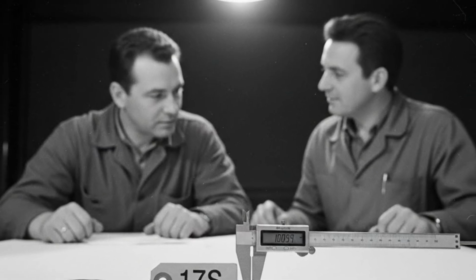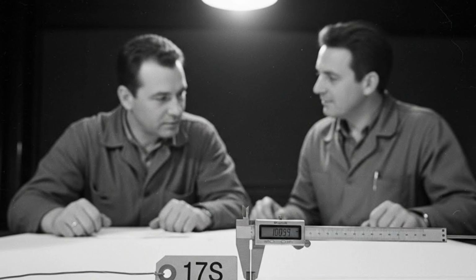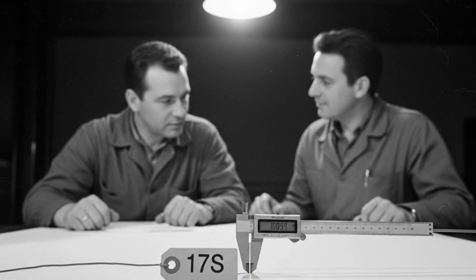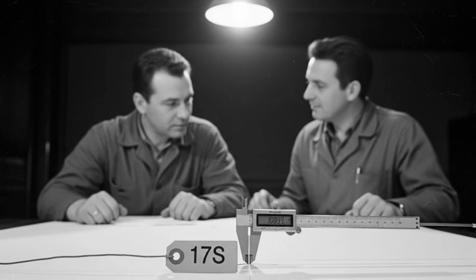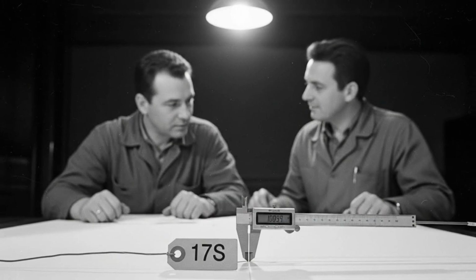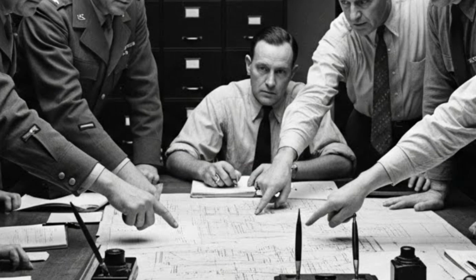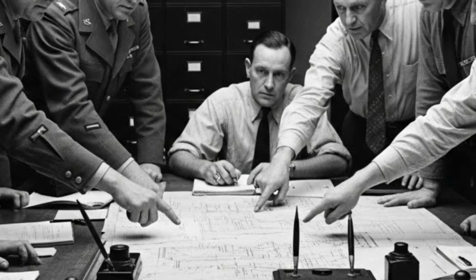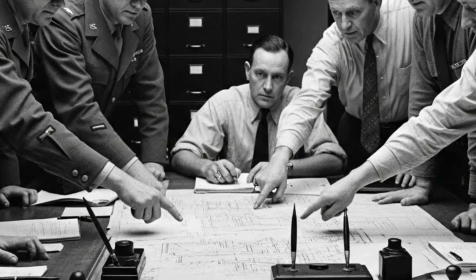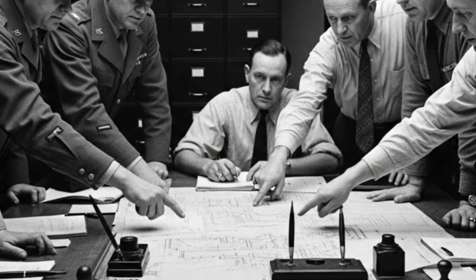Alloys that showed early promise would crack during rolling, the metal splitting like dry wood. Others aged too quickly, growing brittle instead of strong. Some reacted poorly to the heat treatments, warping or developing internal stresses that made them impossible to machine. The fundamental chemistry of what happened inside an aging aluminium alloy remained mysterious. This was 1917, before X-ray crystallography, before electron microscopy, before materials science existed as a discipline. The engineers worked almost blind, guided only by empirical results and educated intuition about how metals behaved. By spring, they had something.